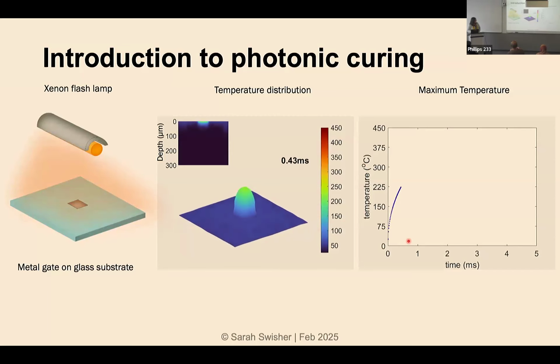So this is a xenon flash lamp that we use. So when this is illuminated, basically what we can see is we're going to look at the temperature as a function of depth into the substrate here, and we'll look at the temperature as a function of space around the substrate surface here. And we'll look at this temperature as a function of time during this pulse. So when the flash lamp turns on, the metal gate that is sitting on top of this substrate is going to heat. Because as you can see, only the region where we have metal is going to heat up.